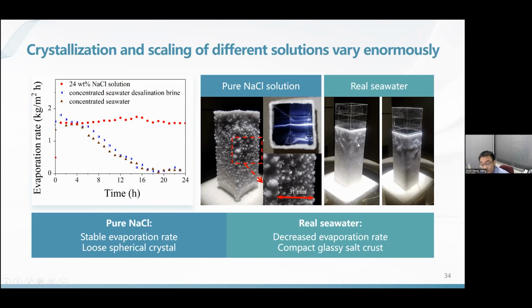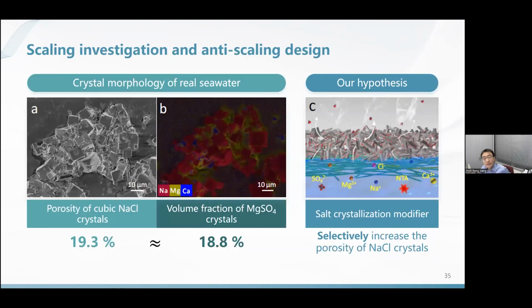And with this very tightly packed crust, there was no space for water to transfer. Therefore, the evaporation stopped. Now, in order to figure out a solution to this issue, we took a lot of SEM images to analyze, to hypothesize what happened. At this point, what we believe happened, or our hypothesis, is this.